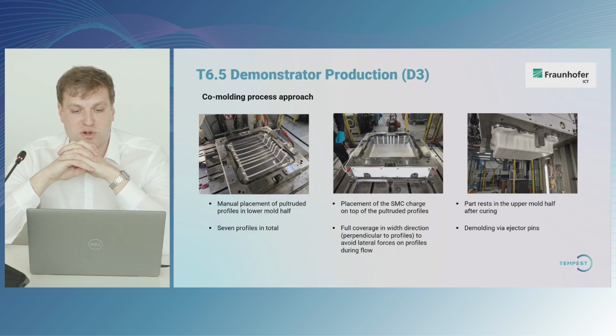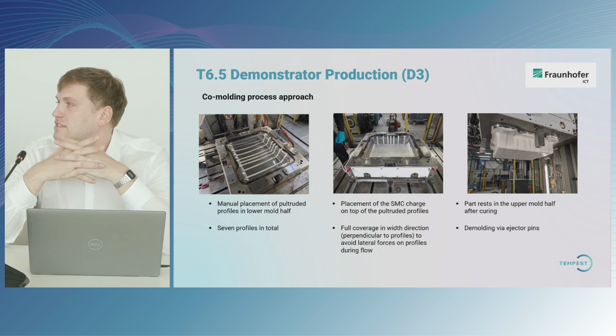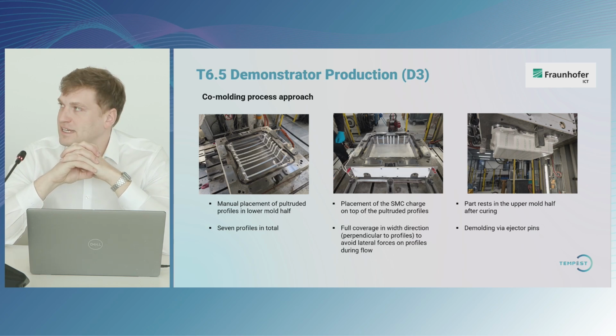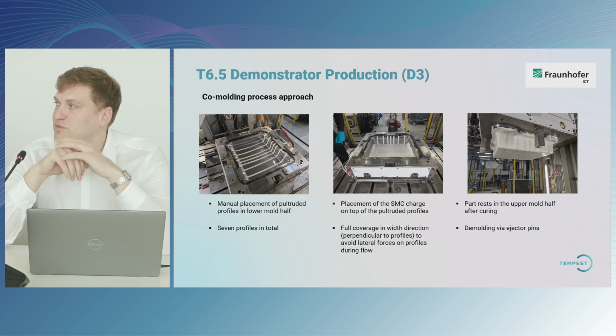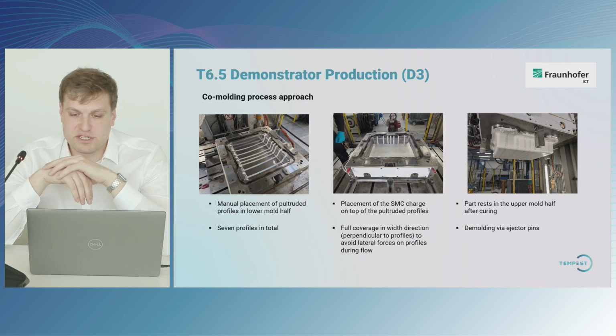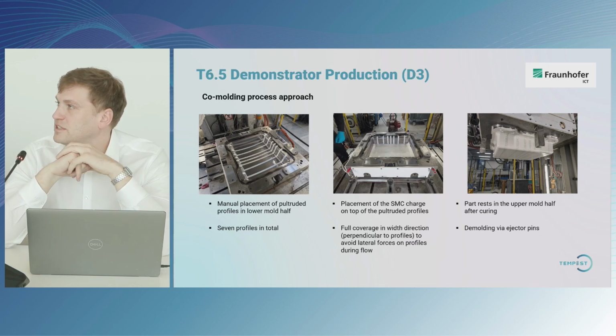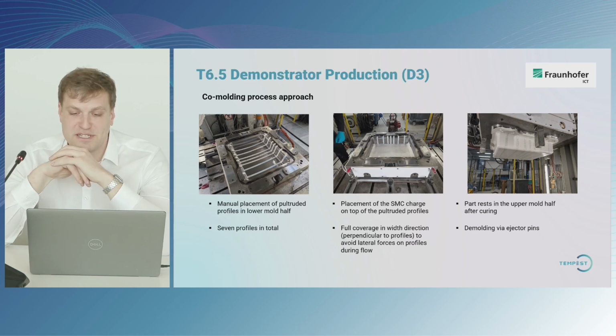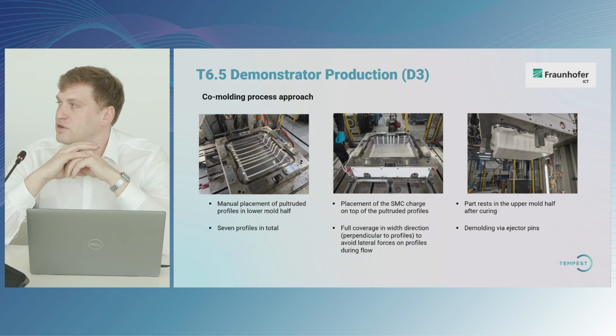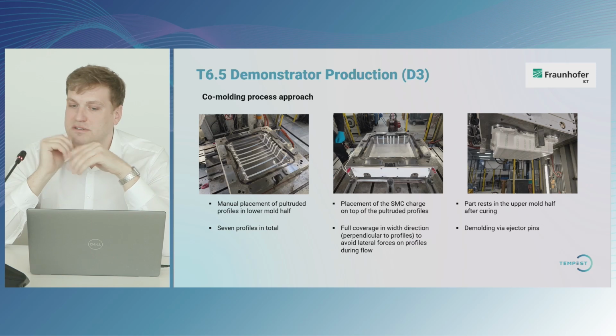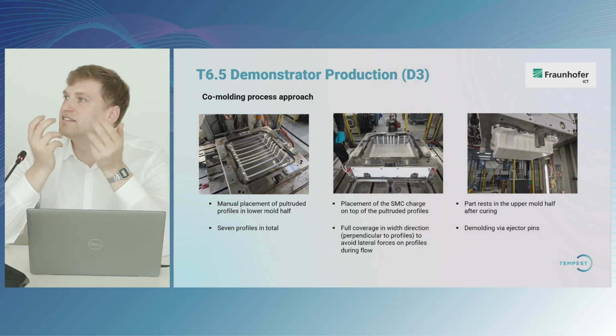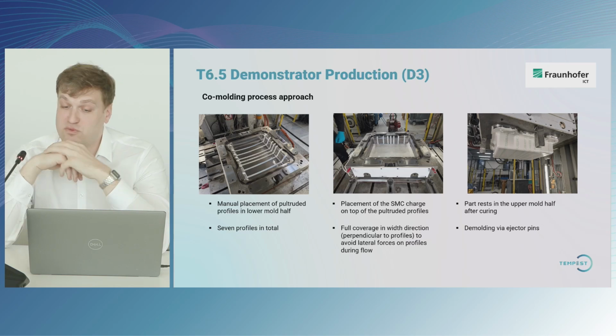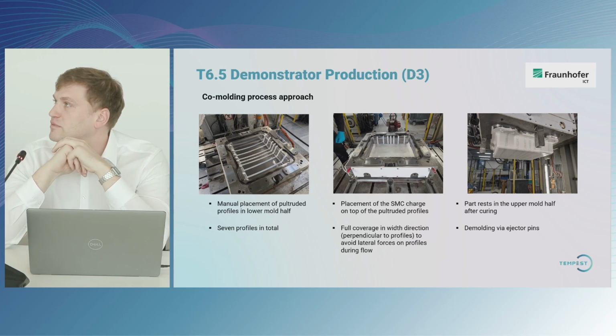So as a summary, the process went really well. We could show that this co-molding is actually possible with a mono material system. With the Elium itself, it was quite challenging with the demolding, which is, as you might have noticed earlier in the LCA, why we changed to another material, an SMC standard thermosetting material, just to make sure that we have enough test specimens. However, we are looking at surface treatment as well as additional additives like curing agents to make sure cross-linking goes faster, so that you increase the bonding. We are still looking into manufacturing it, as this is one of the few thermoplastic approaches, and we are really keen that we can make it with Elium as well.